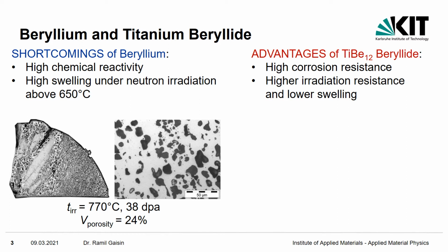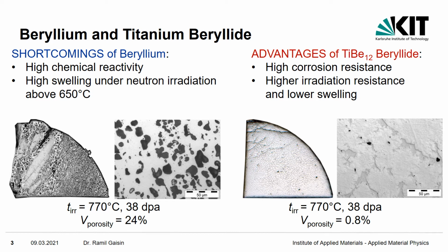This intermetallic compound, called titanium beryllide, has much higher operating temperatures due to better corrosion resistance and due to much lower swelling. Under the same irradiation conditions, beryllium looks like Swiss cheese on the left, and beryllide has almost no porosity on the right.